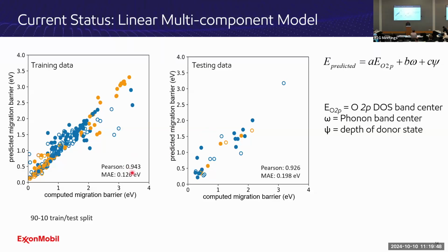And the great news is we don't have to be that accurate. So what is my accuracy goal here? Something on the order of 0.2 eV, that's pretty good. So if I have 50,000 oxides and I want to narrow down to some subset of oxides that I want to actually test for oxygen transport, and let's say I want the barriers to be in the range of 1.1 to 1.3 eV, well, now this generates that set. I don't have to be super accurate in this particular case on the diffusion side.